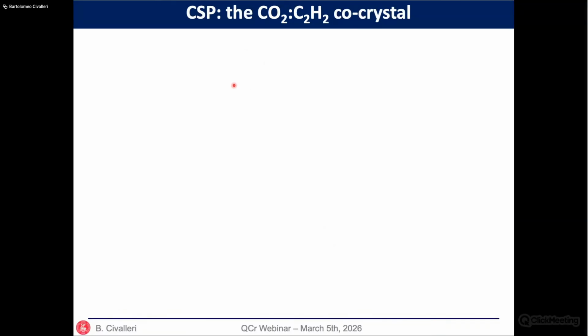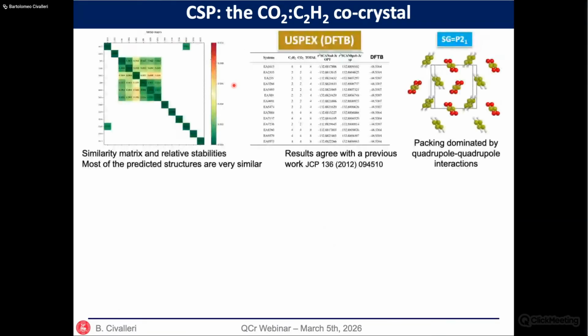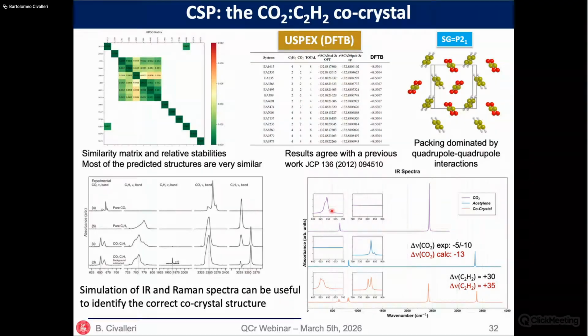So this is carbon dioxide mixed with acetylene, and we use USPEX with DFTB to run most of the calculations, but then we refine the results with our composite method, and we end up with a structure that is not unexpected because the packing is dominated by quadrupole interactions. In this case, we then compare the infrared spectra, which is very useful to check if the structure is well predicted, with respect to experimental data that have been published some years ago.